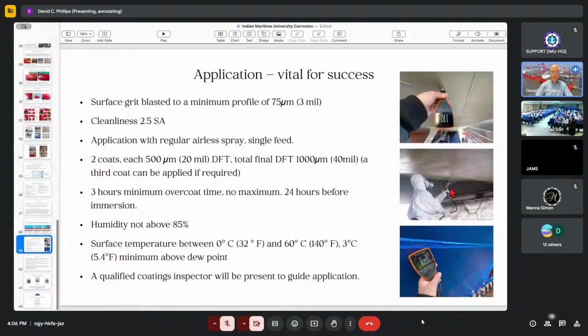With epoxies, it's a very tricky overcoat time. You've got to overcoat it at the exact right time, and the first coat has to be slightly tacky when you put the second coat on, or it doesn't bond properly. With vinyl ester, you don't have those problems at all. You can put it on after 3 hours, you can put it on after 3 days, you can put it on after 3 weeks without re-preparing. Very useful for shipbuilding, particularly.